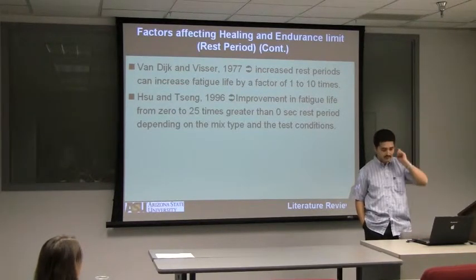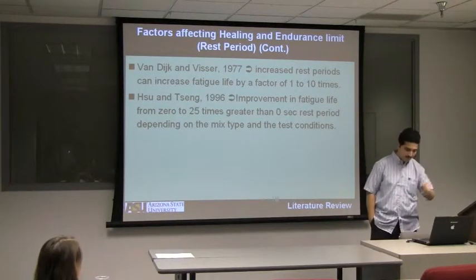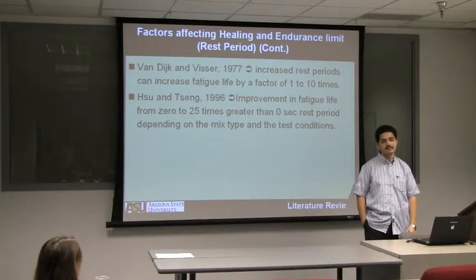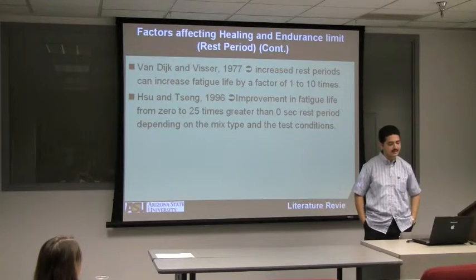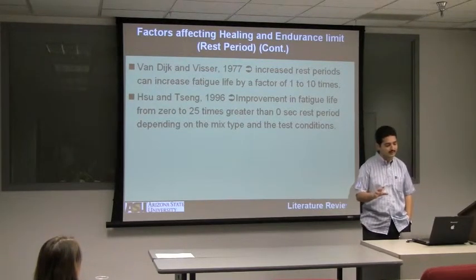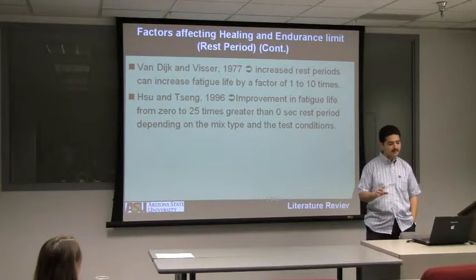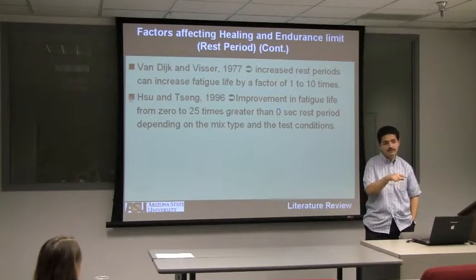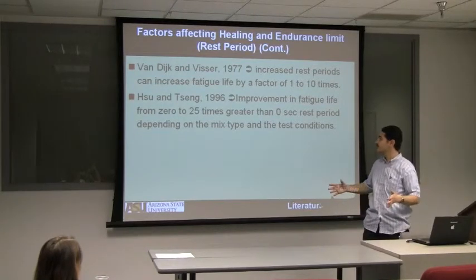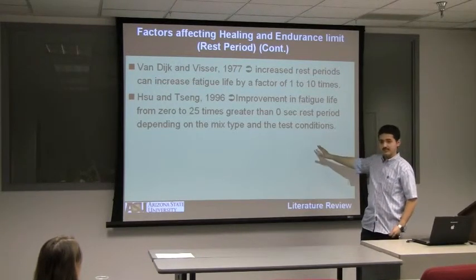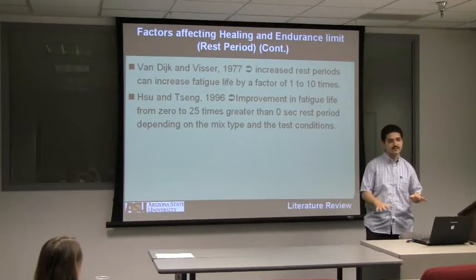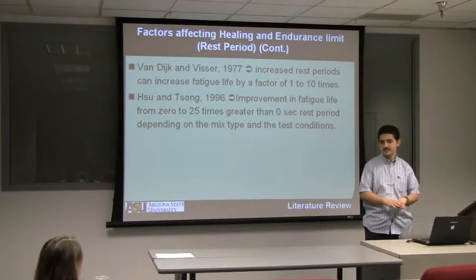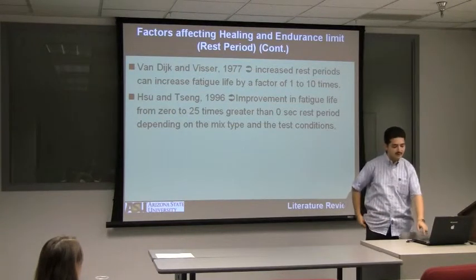This is one of my favorite quotes because this strengthened my hypothesis from the beginning that the endurance limit changed. So what Hsu and Tseng did, they showed an improvement in fatigue life when they apply a rest period. And this improvement was from 0 to 25 times compared to not applying any rest period. But they say this improvement will depend mainly on the mix type and the test conditions. So the endurance limit is not constant. It's going to keep changing by changing your mix design or the testing conditions.